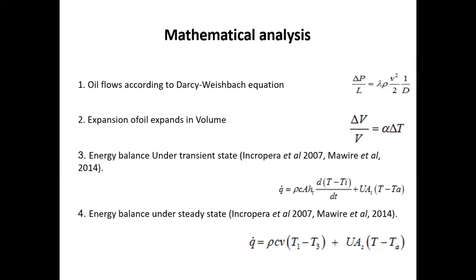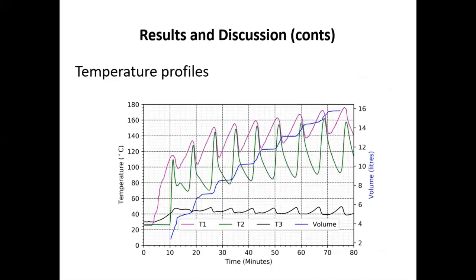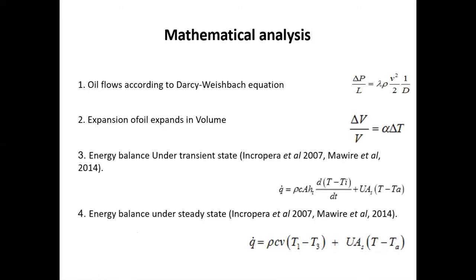So you have two possible scenarios, the transient state and the steady state. In the transient state, that's when there is no flow, the energy balance is governed by this equation. And then in the steady state, we have a flow, and the energy balance is governed by this equation. The first term has rho, which is density, C, specific heat capacity, A, the cross-sectional area of the heating chamber, HT, the height of the heating chamber, T, the average temperature at a given time, and Ti, the initial temperature.